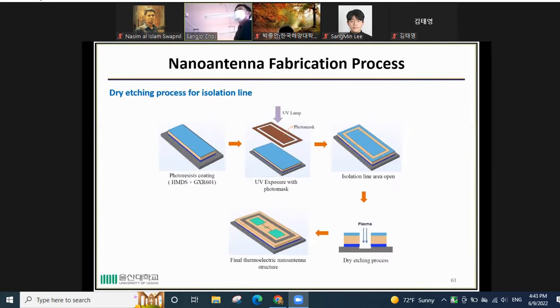And the last process is the isolation line. Since we fabricate many nano antennas on one substrate, we need to provide an isolation line for better electrical insulation. So we also start with the photoresist coating, and we use UV lithography by exposing the sample. And this is the isolation area opened, and then we perform dry etching using reactive ion etching. And then after that, this is the thermoelectric nanoantenna structure, and these are the etching lines to provide good electrical insulation between one device and another device.